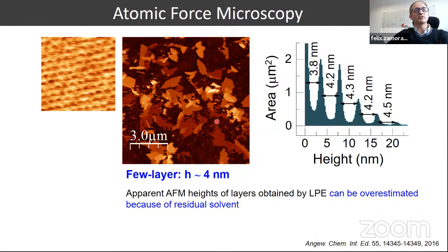In any case, we characterized the material that we got in this suspension by, for instance, atomic force microscopy. When we drop casted this substrate with our suspension, we observed that we have a lot of layers with relatively large lateral dimensions, and with a step height of about 4 nanometers. We eventually have atomic resolution telling us that we have a nice crystal quality of our material.